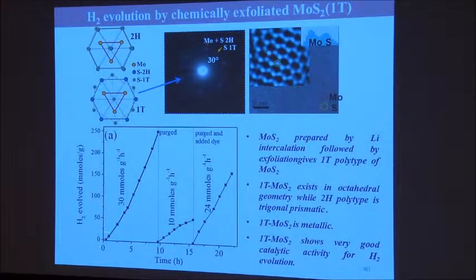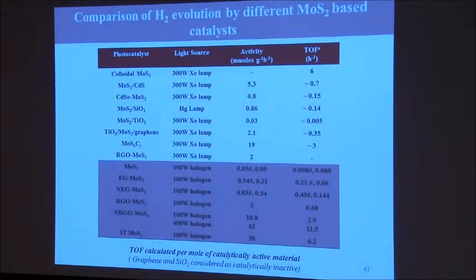As soon as we make it, look at the amount of hydrogen that we start getting—it was really unbelievable, this result. This is just completed. Ordinary MoS2 with a 100-watt halogen lamp gives a very small amount of hydrogen, very low turnover factor. Do it with graphene—slight improvement. With nitrogenated graphene—not bad, slight improvement.